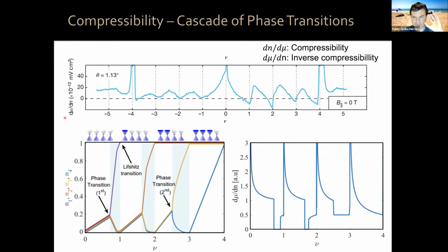So in a very simple picture, what you can think of is the following. I have these 4 flavors: spin up, spin down, valley K, valley K prime. And when I start from charge neutrality, as I add charge to the system, those flavors start getting filled. Initially, all of these flavors get filled at the same time, at the same rate. Now, when I'm close to total filling factor 1, that means when I have about 1/4 of each flavor filled, the system spontaneously flavor polarizes, sends all the carriers to one flavor and empties the other 3 flavors. It becomes flavor polarized.